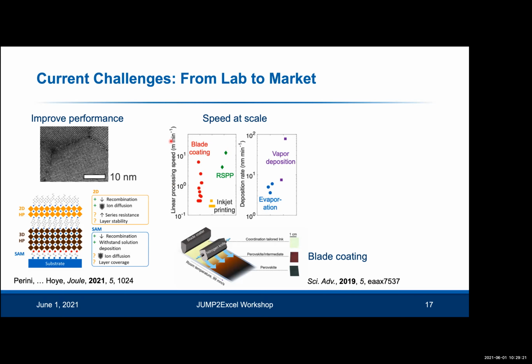So this compares the processing speed for various large area deposition technologies. And you can see that one of the fastest technologies is this rapid spray plasma processing technique. And there's also blade coating, which is what you see here.